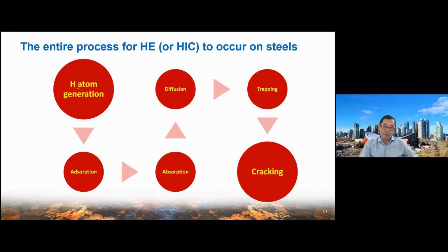The first one, as I just mentioned at the beginning of my talk, hydrogen embrittlement means hydrogen-atom-induced embrittlement. So that's why the first step is how hydrogen atoms are generated from the environment condition. After hydrogen atoms are produced, they will touch the steel surface. That's the second step, adsorption, ADS. ADS hydrogen will go inside the steel and become absorption, ABS hydrogen. That's number 3. When hydrogen goes into the metal, it tends to diffuse in the crystal lattice of the steel. That's diffusion, number 4.